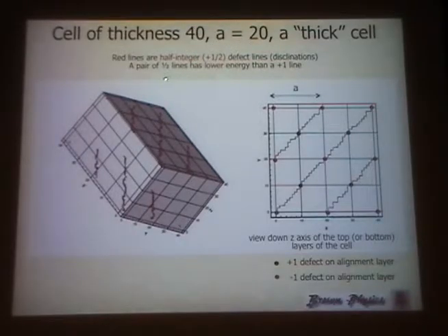And what you're seeing is that yes, there are disclination lines, so you were right to think that. But in fact, in this case, I think this was like a quarter, the 25% said, well, yeah, there are disclination lines, but they're not threading through the cell. In fact, what they are doing is coming out of these point defects on the alignment layers.